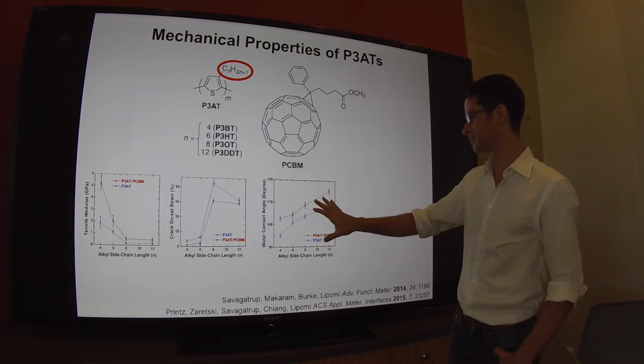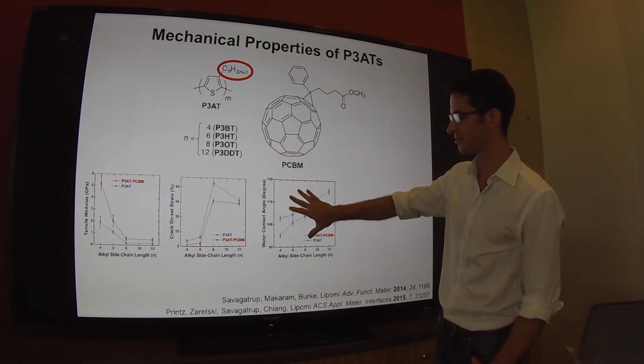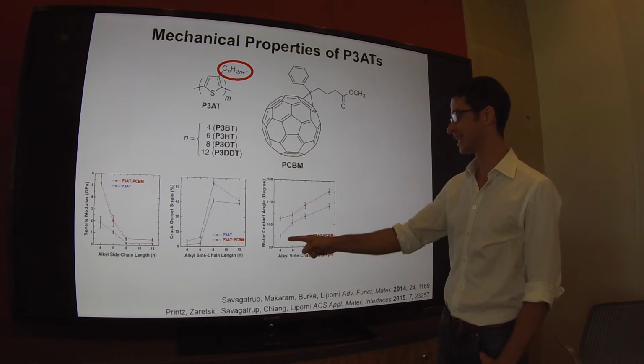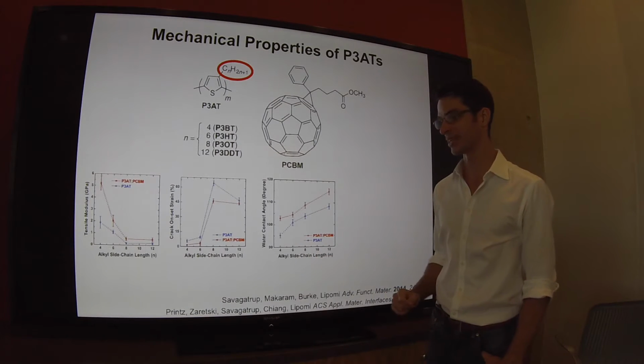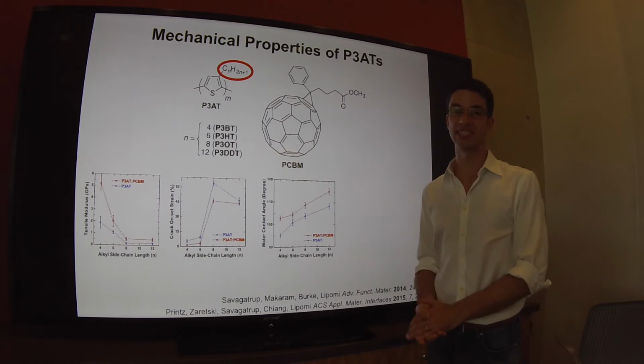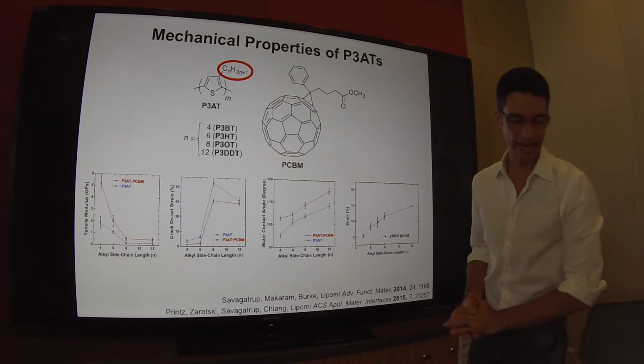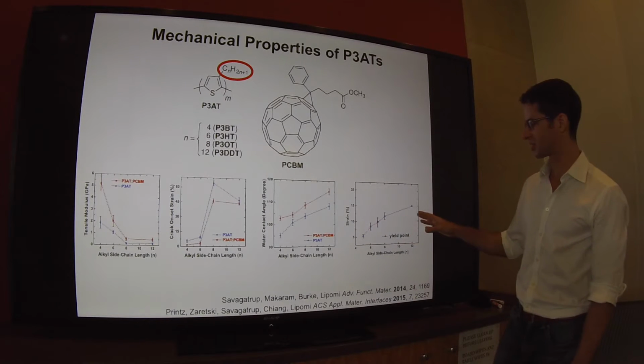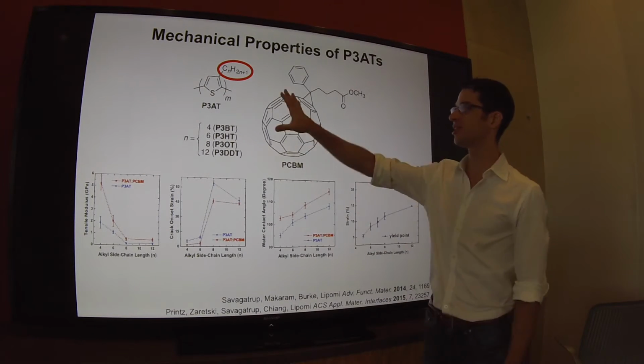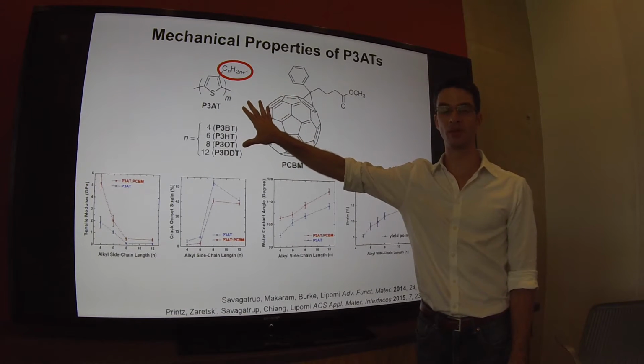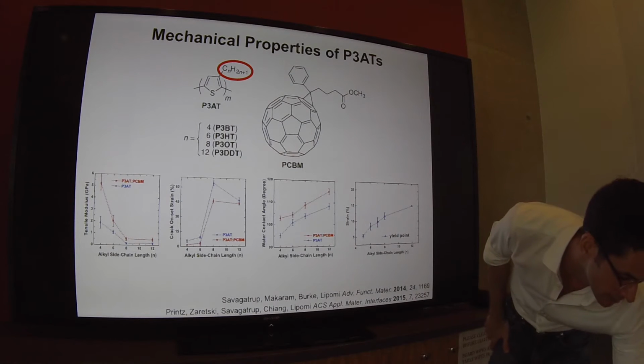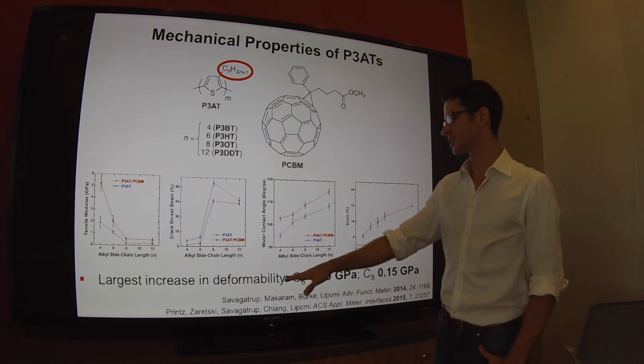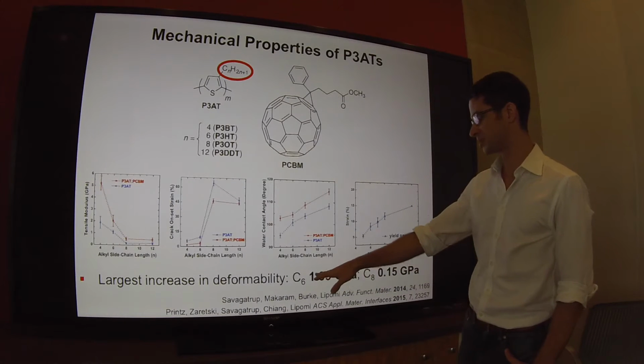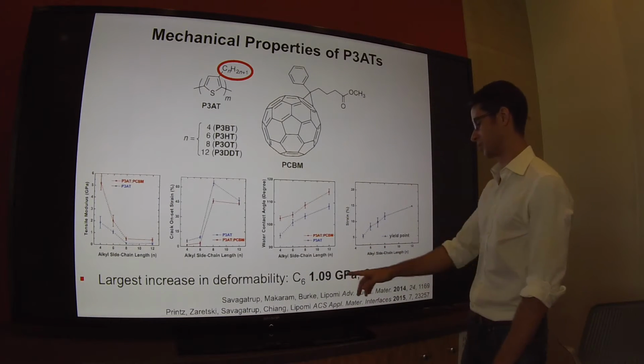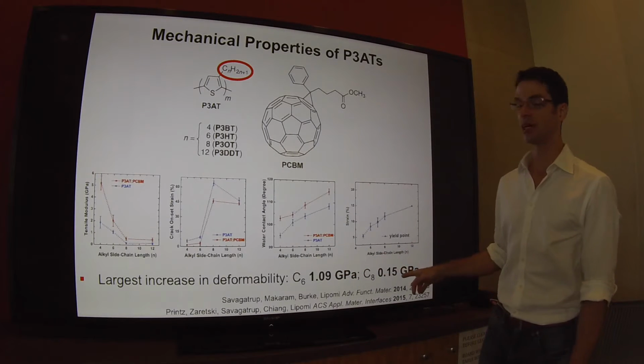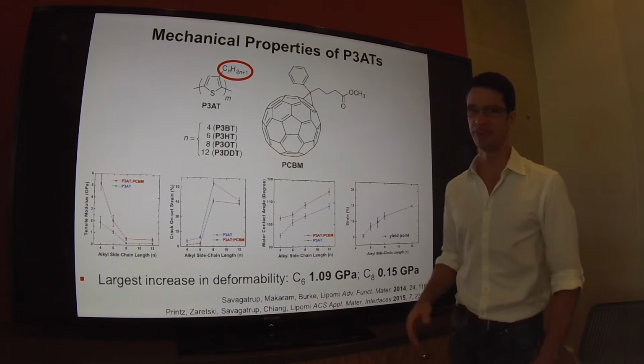And this is consistent with the fact that the water contact angle increases as a function of the alkyl side chain length, which is usually consistent with poorer adhesion. If you look at the strain at which yield occurs, we see an increase in yield point. Now this is all approximately the same molecular weight, about 30 to 40 kilodaltons. And we note again that the largest increase in deformability occurs between the C6 to C8 transition, where the modulus goes from over a gigapascal to about 150 megapascals.